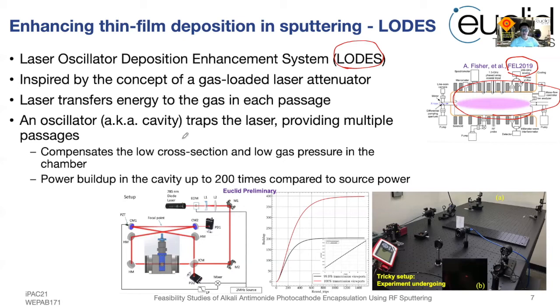We had, in our phase one work, developed this system shown in here, which builds a laser cavity. In the cavity, we can have some buildup of the laser, which can get up to 200 times if you consider a realistic viewport transmittance. This will effectively turn a 0.1 milliwatt laser into a 20 milliwatt laser.